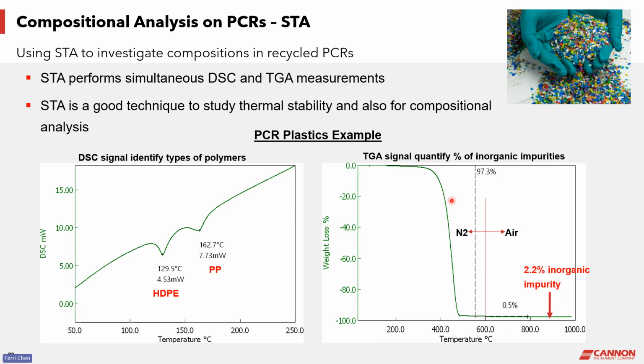In the meantime, the TGA part of the analysis allows us to identify the percentage of inorganic impurities. From this figure here, we can see that both PE and PP degrade at temperatures above 400 degrees C. And then we switch the gas purge from nitrogen to air, to further burn down additional carbon. After that, there are about 2% of residues that cannot decompose in the testing temperature range. So this result tells us that there are about 2.2% of inorganic impurities in this recycled plastic resin.